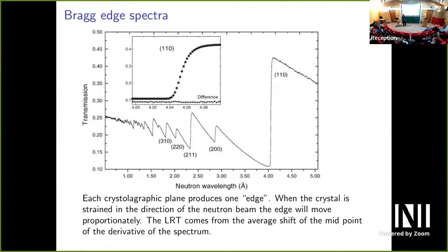And what you get for such an experiment, for one ray, is a time of flight graph of the number of neutrons you measure, and it's put in wavelengths, because wavelengths relate to frequency and energy, and therefore ultimately length scale.